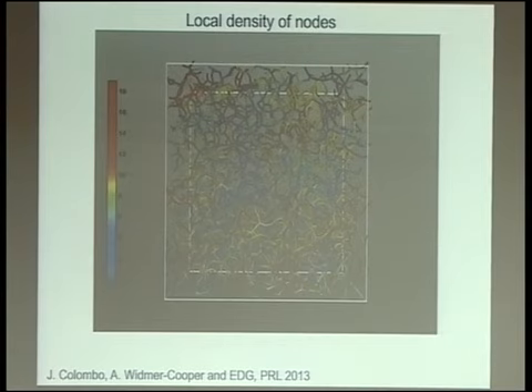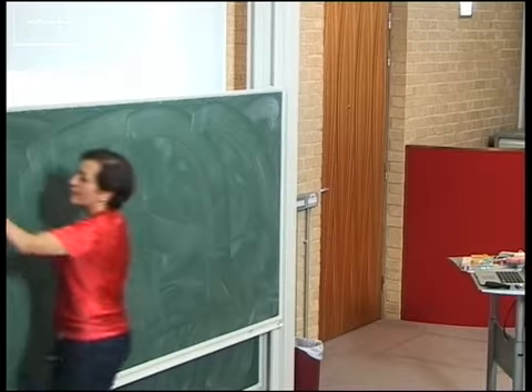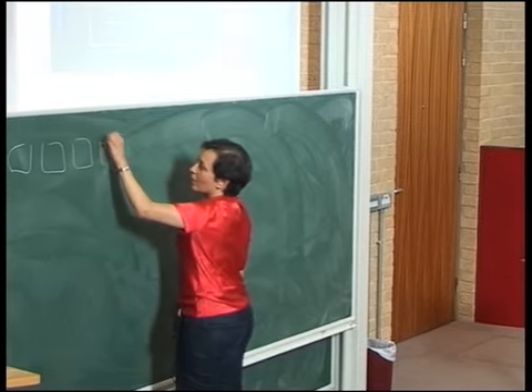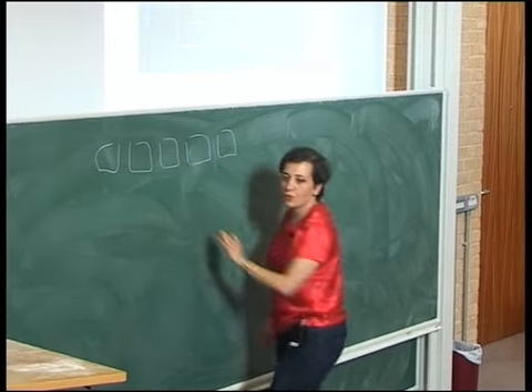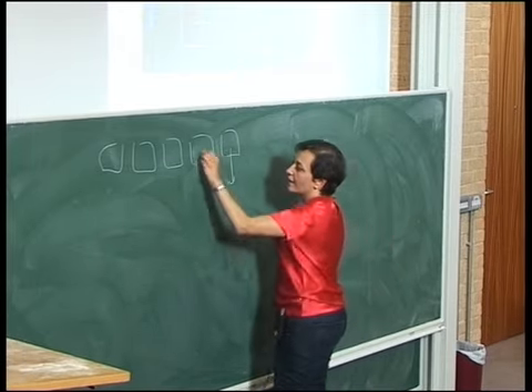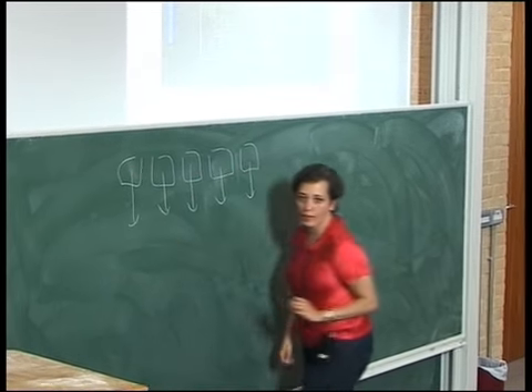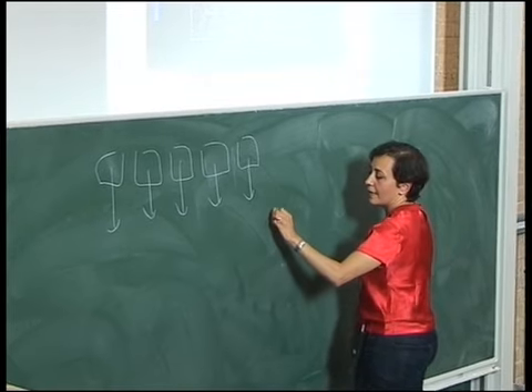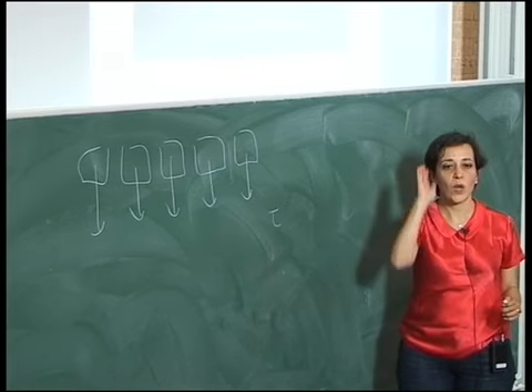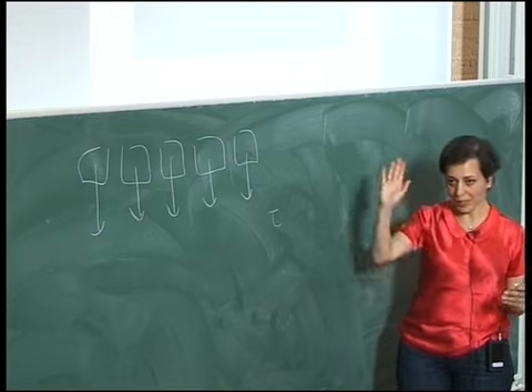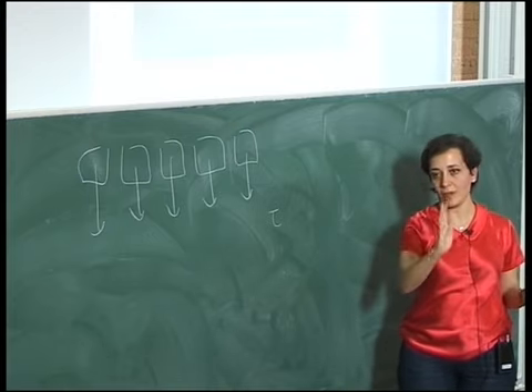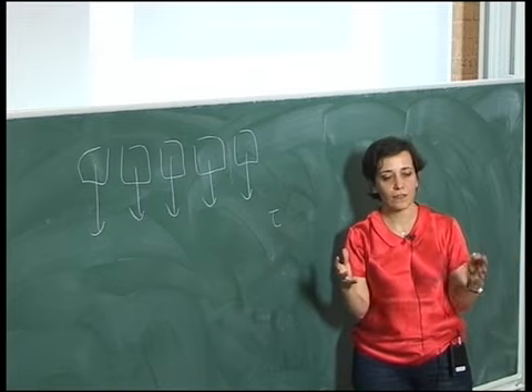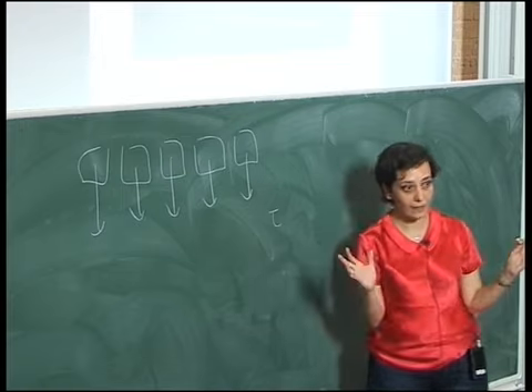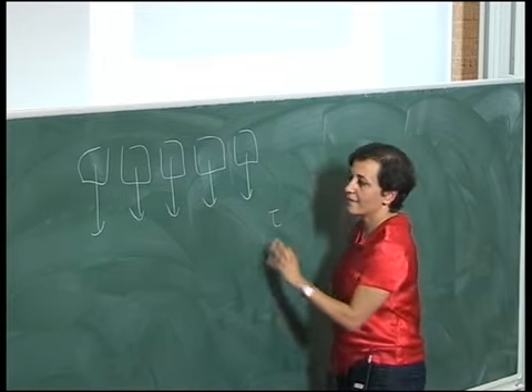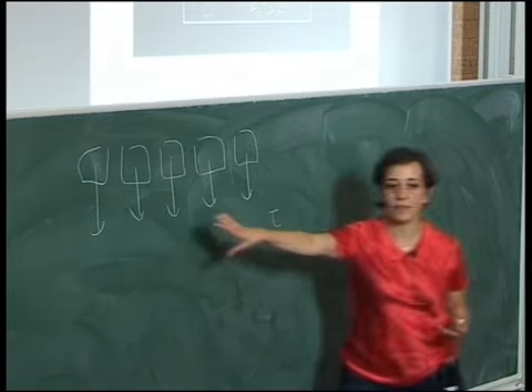So now, what we have done is this isoconfigurational ensemble analysis that I was explaining before. I have copies of my system, with the same particle configuration and different initial velocities, and then I evolve each of these copies just with molecular dynamics. Then I take a characteristic time, where I saw this peak in the cooperativity. I want to look at that time scale, right? This is the time scale that is interesting for the reorganization of the network, where interesting things happen at that level. And I look at the spatial distribution of dynamical quantities over this sample, okay?